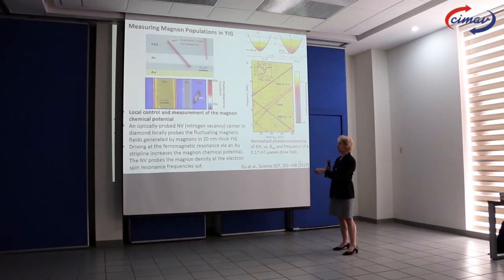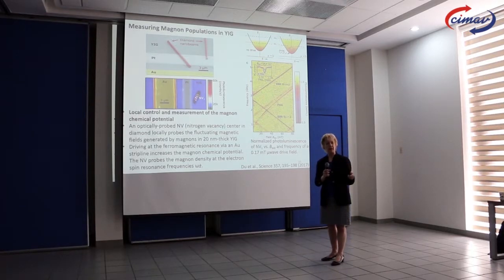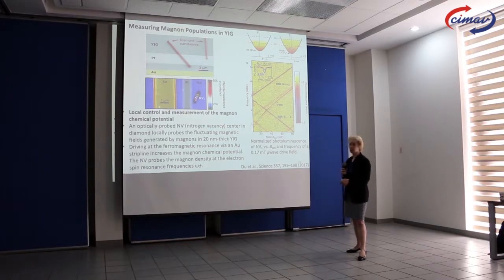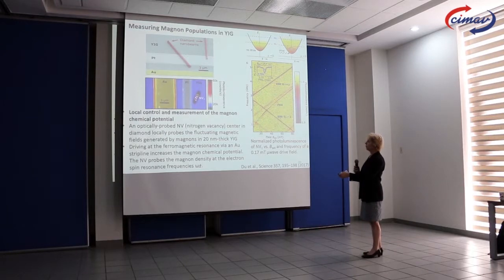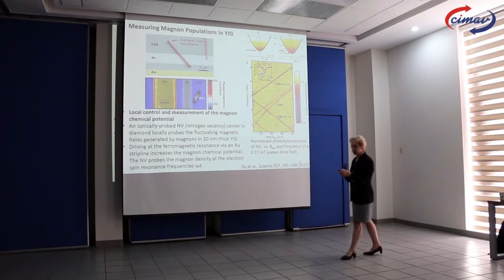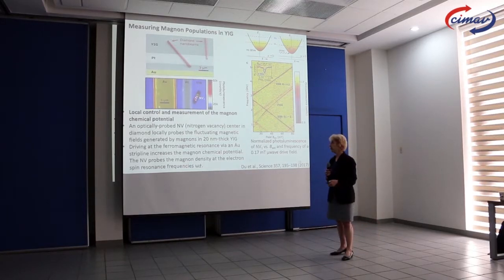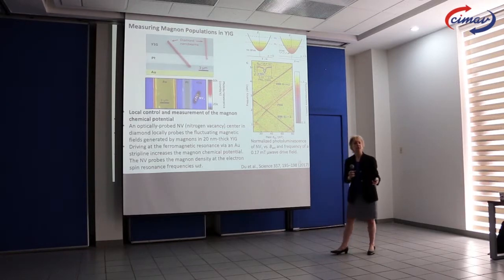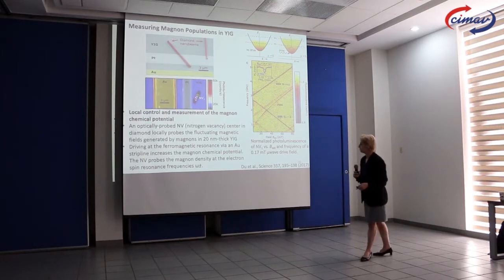The diamond has a defect in it, which is a nitrogen vacancy defect. There's a nitrogen atom and a vacancy adjacent to each other. And that NV center is actually a very good detector of small magnetic fields. So you can probe it optically, and you can use the response of that NV center to detect magnons in the YIG. So this gives another method of detecting and producing magnons compared to those coplanar waveguides.